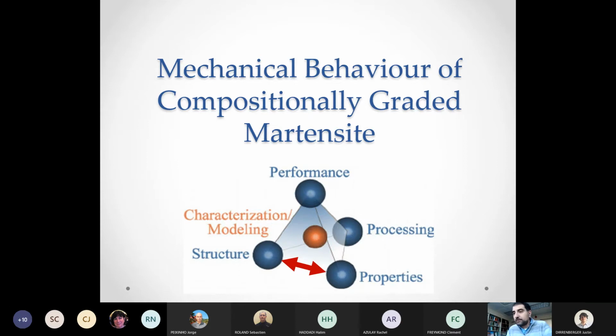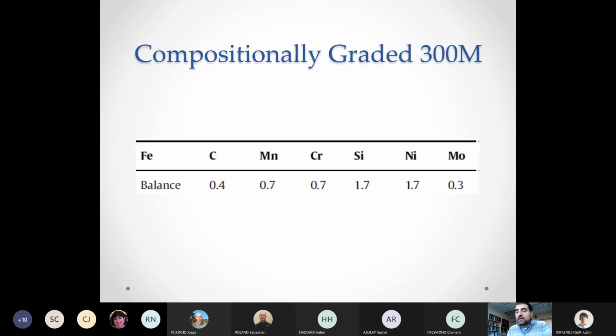And now I will try to give examples of what kind of properties we were able to achieve from these interesting microstructures. So the first point to emphasize here is the alloy we're going to use. We used an alloy called 300M. It's very similar to 4340. The main difference is it has high silicon content, which makes it more difficult for carbides to form at low temperatures. And the other key point is it has 0.4% carbon, so a medium carbon steel.